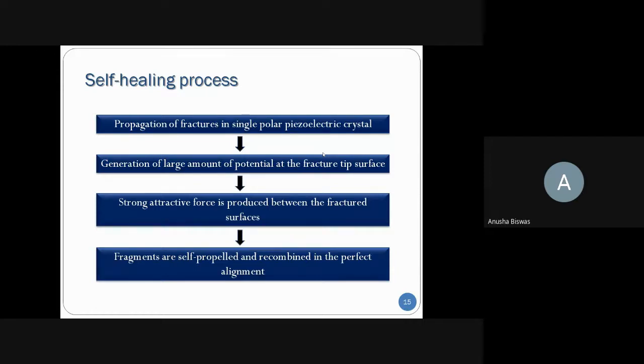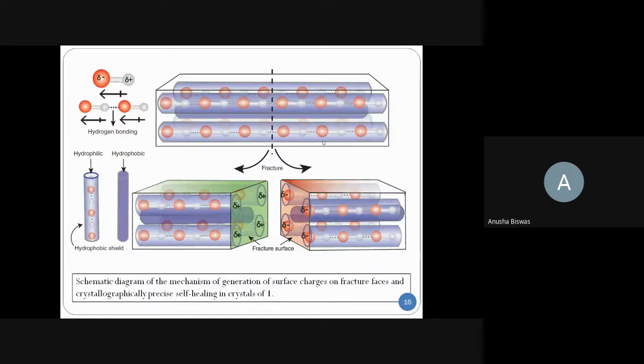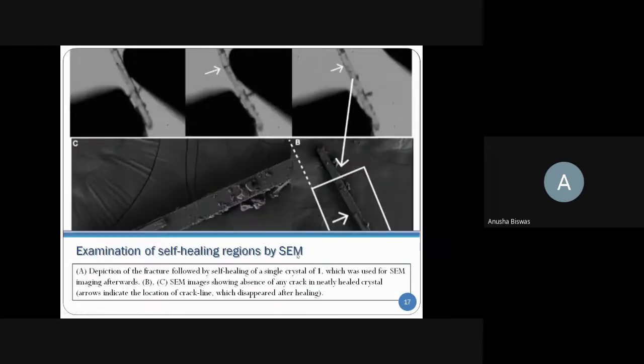The self-propelled part travels with an acceleration of nearly 2.2 meters per second squared, and the time required for this reassembly is 2 to 3 milliseconds. This is a schematic diagram for the generation of surface charge and the self-healing process. Here the crack is introduced and here the piezoelectric effect leads to generating this opposite charge in these two faces, which will lead to an attractive interaction between these two, and these two parts are joined in a perfect manner. This is the scanning electron microscope image of the self-healing crystal. Here the crack is introduced and after 2 or 3 milliseconds this crack has disappeared. Therefore it's a neatly healed crystal, and it is zoomed here. Now this is a video of the self-healing process of this material.